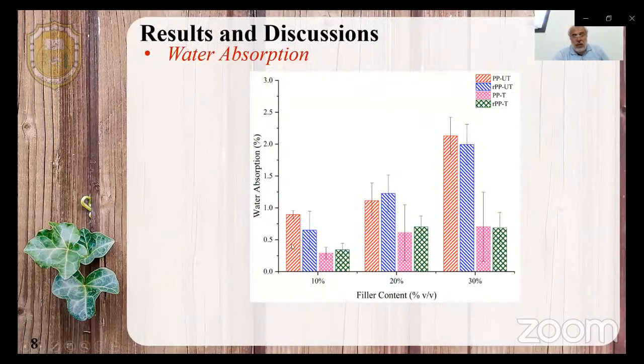For the water absorption, as we can see in this graph, the filler content is plotted as a function of the water absorption. We can see the recycled PP based biocomposite has less water absorption. When we do treatment, the water absorption will be cut more. It will increase, of course, when we increase the fiber content, because the filler will absorb more water.